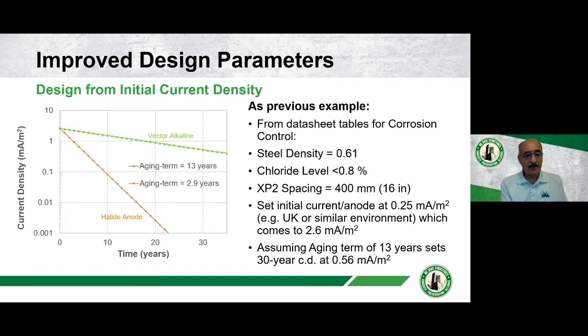Just showing that graphically, basically the same thing. This is the first case where we're working the spacing from the tables, 400 millimeter spacing, 16 inches, for a less than 0.8% chloride concentration, steel density 0.61. Our current density will be 2.6, and we can follow the trend using our half-life concept of 13 years, and this will be the current as it drops with time. But we still have significant current after 30 years.